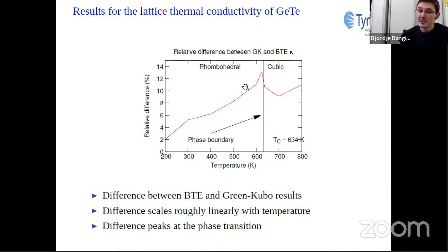We also notice that the difference scales roughly linearly with temperature, which we might expect because phonon self-energy scales roughly linearly with temperature. Also, the difference peaks at the phase transition, which is also understandable because we expect germanium telluride to be most anharmonic at the phase transition.